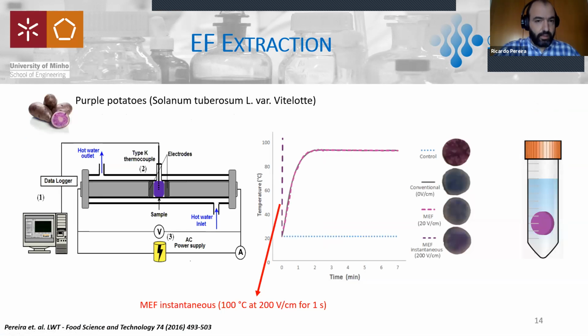Another example was with extraction of phenolic compounds from purple potatoes, and in this case we also reduced use of solvents during the treatment. The potato pieces were placed directly into the reactor. We applied several strategies of treatment, such as instantaneous heating. We can go up to about 100 degrees in less than 1 second. Or we can also process the samples with treatments that are not so aggressive, but take more time to perform. So depending on this, we can have different outcomes.